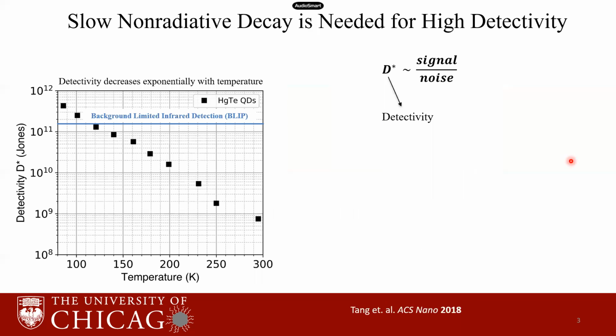Quantum dot infrared cameras currently are good but not great. And the main challenge faced by these quantum dots is that they need to be cooled to cryogenic temperatures to operate. Here we have the detectivity versus temperature for mercury telluride quantum dots, which are the most common quantum dots used for thermal detection. On the y-axis, we have the detectivity D star, which is a measure of the signal to noise. And this tells about the performance of the detector.